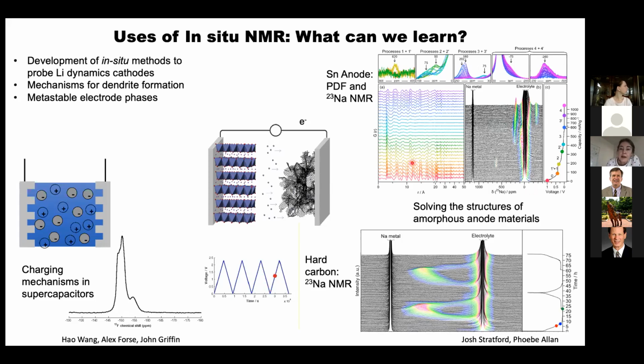And this is another example of another potential sodium anode material, and that's tin. And these are very attractive because you can react sodium with tin to get very, very high capacities. I'm going to have to put my glasses on for this one, you can just about see how high the capacity is. You're getting 1,000 milliamp hours per gram out of tin, whereas in carbons, you would get no more than about 300 milliamp hours per gram.